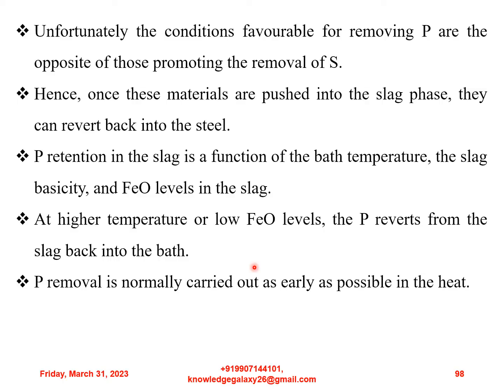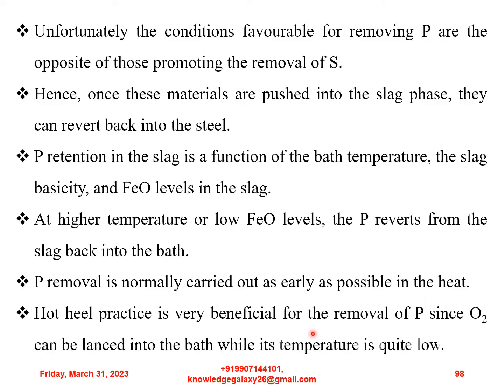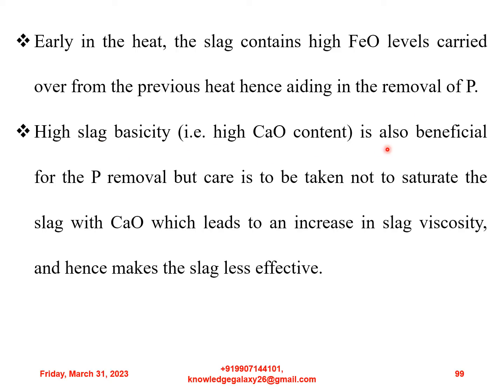So now moving on. Phosphorus removal is normally carried out as early as possible in the heat. Hot heel practice is very beneficial for the removal of phosphorus, since oxygen can be lanced into the bath while its temperature is quite low. Early in the heat, the slag contains high FeO levels carried over from the previous heat, hence aiding in the removal of phosphorus. High slag basicity, that is high CaO content, is also beneficial for the phosphorus removal, but care is to be taken not to saturate the slag with CaO, which leads to an increase in slag viscosity and hence makes the slag less effective.